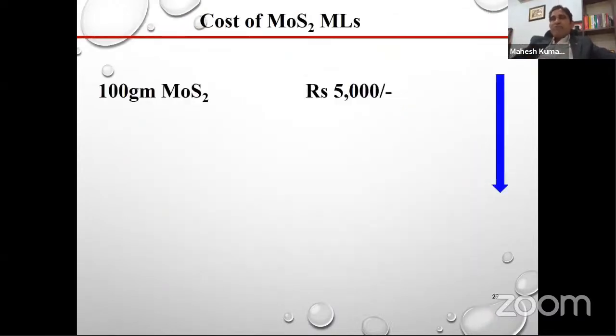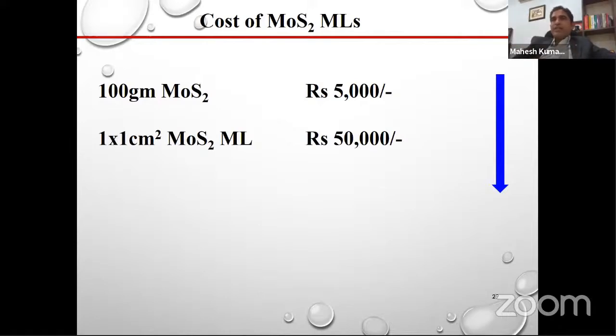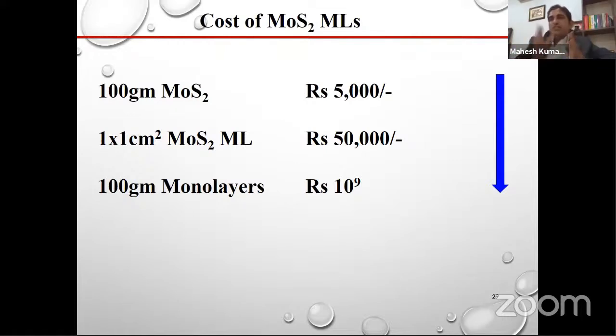If we buy, for example, MoS2 from Sigma Aldrich, 100 gram costs 500 rupees. But if you buy a 1 centimeter by 1 centimeter square MoS2 monolayer, then the cost is 50,000. And if we separate all the layers from 100 gram into monolayers, the cost will be around 1 billion rupees. So to go from 500 rupees to 1 million, we just have to separate out these layers. That means separating these layers or growing these monolayers is not so easy. Otherwise, any manufacturer could easily separate them out. So this is very difficult.